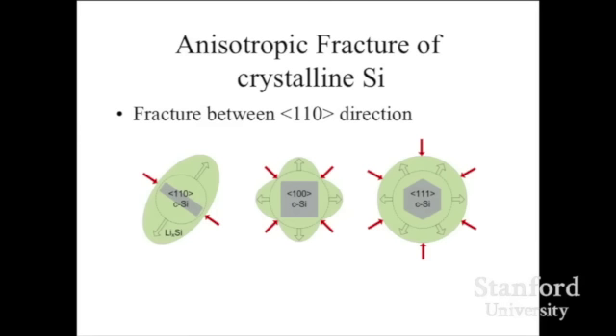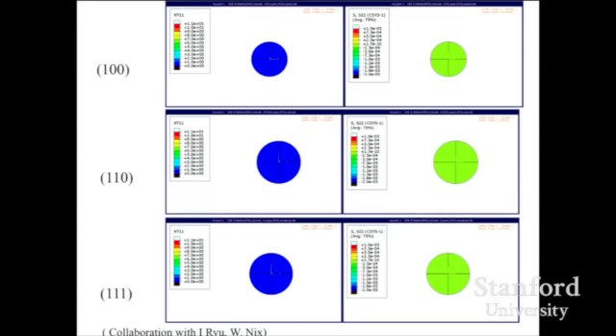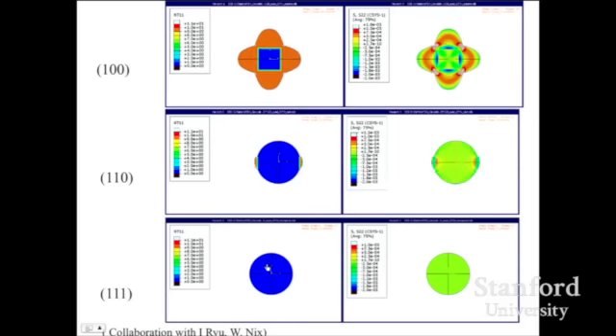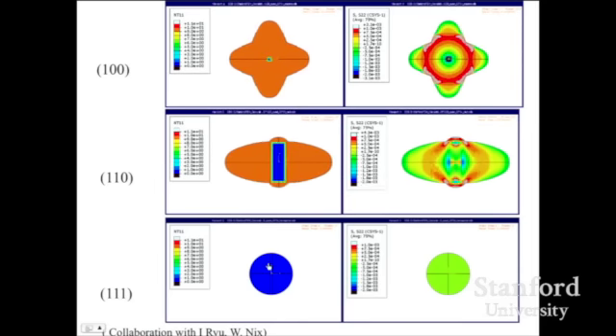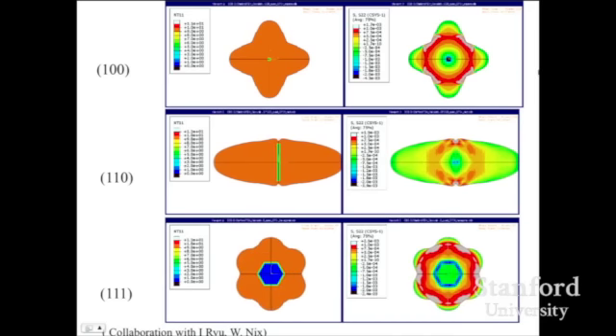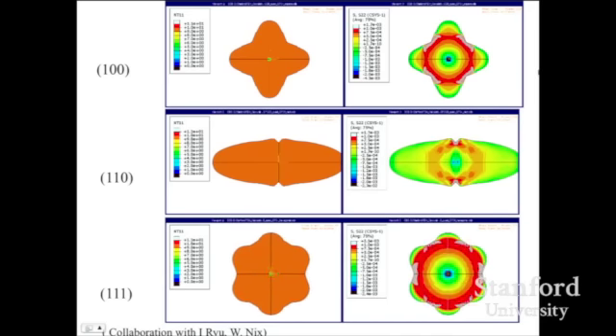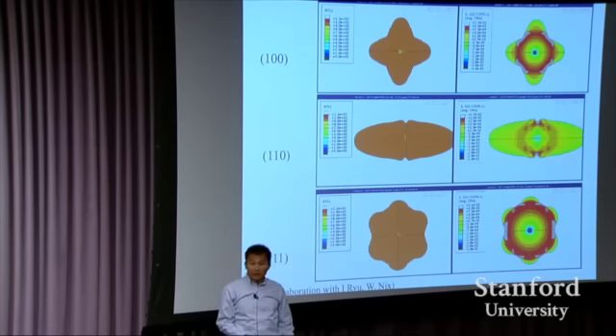So this expansion is really interesting. So I'm going to skip through this very quickly. But I want to show you this anisotropic volume expansion has a significant meaning right here. This is a simulation done in Bill Nix group. You look at this anisotropic expansion, look at the stress profile. The stress really concentrates between the two expansion directions. That's the tensile stress right there. That's where the breaking point happens, exactly. So the breaking doesn't happen in a random position, it happens in a fixed position.